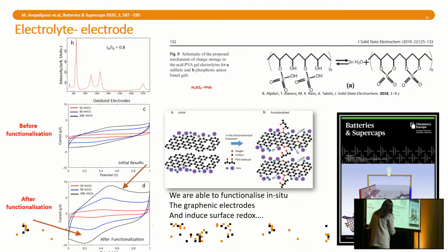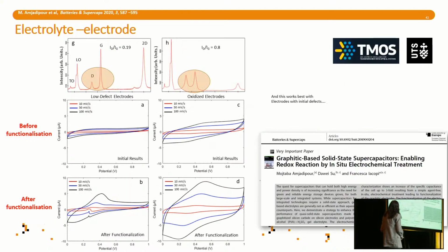And so we showed that we could do that in situ, and I won't go into the detail, we can also create some Faradaic, some redox reactions in addition. So we can actually go from not fantastic performance to a 3 times higher performance. I won't talk about that. This is just to show you that in this case, it's good to have a lot of defects, because the more defects you have, the more this effect will be important.